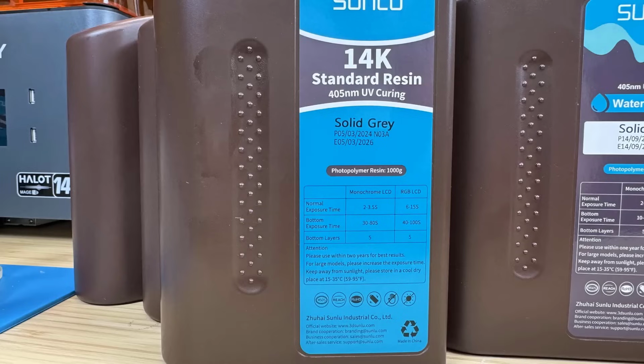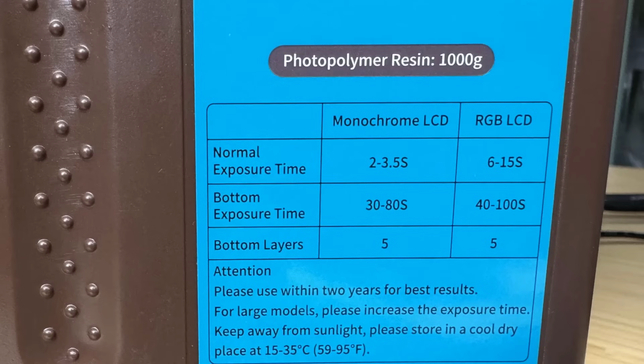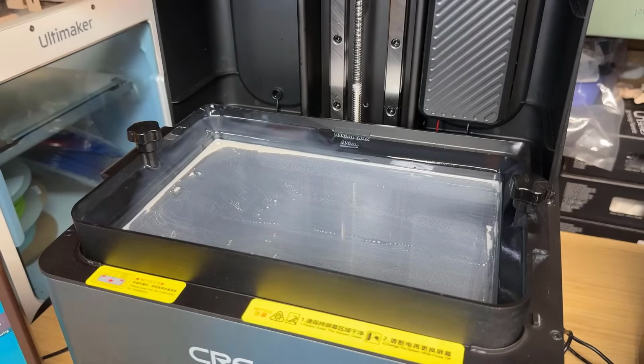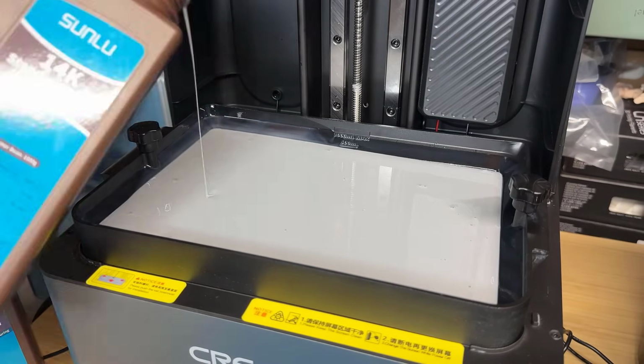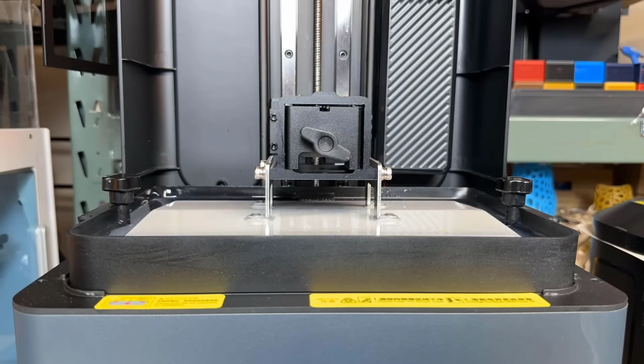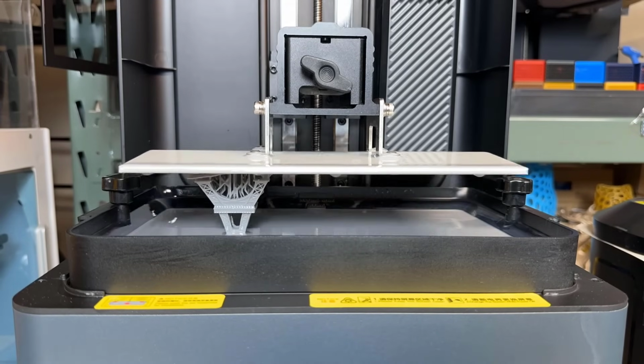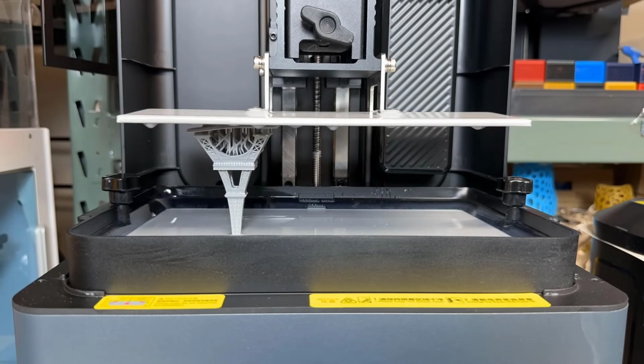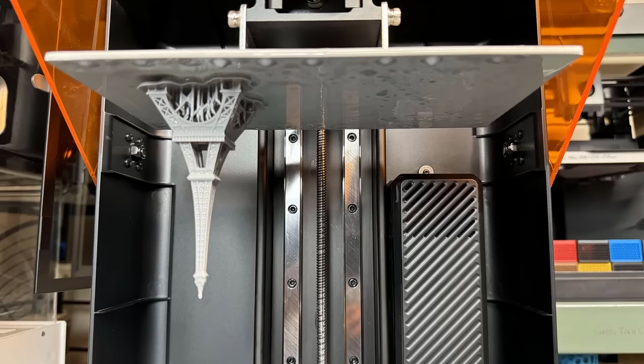Up next, I'll test the 14K high-resolution resin. The exposure time for the regular layers is the same as for the standard and water-washable resins, but it seems to require a much longer time for the first layer. Although the recommended minimum time for the first layer is 30 seconds, I'll keep my settings and see what happens. All the models fail to stick to the build plate, except for the lighter Eiffel Tower.